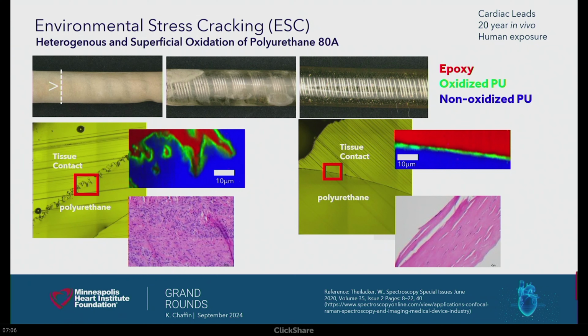And what we were able to do, if you look at this white cross-section here, we were able to cross-section that lead. We embedded it in some epoxy, and then we were able to go in and look at the tissue contacting surface of that polyurethane as opposed to the inner surface. And then we were able to go with an experimental technique called Raman spectroscopy, and we can distinguish between oxidized polyurethane and unoxidized polyurethane. And what you see is I've colored the oxidized polyurethane green and the unoxidized polyurethane blue. And we noticed that we had these white areas with all of this surface topology, and they're white, they refract light, they're not a smooth surface, but that oxidation layer is really quite, it's like the perimeter of Lake Minnetonka, right? It moves around that surface, but it doesn't seem to get thicker with time, which we didn't know. We didn't understand that.